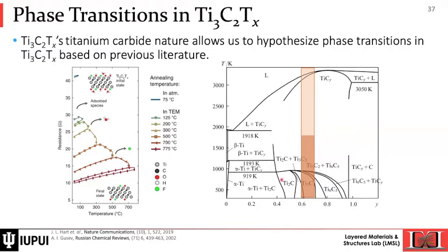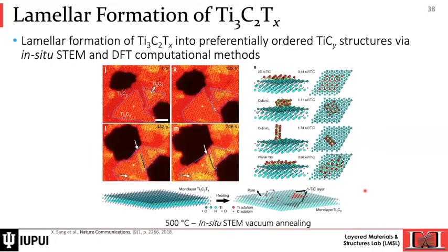And we are in the non-stoichiometric phase diagram. So now we can use MXene as a precursor to design novel structures that are traditionally impossible to make for high temperature materials. The first study of the phase transformation was done in 2018 from Oak Ridge National Lab in collaboration with Drexel University. It was shown that when we heat treat MXene Ti3C2 at 500 C in situ STEM in vacuum, we have homoepitaxial growth of MXene, meaning that we'll have layers of titanium carbide forming over a MXene and make it thicker and thicker.